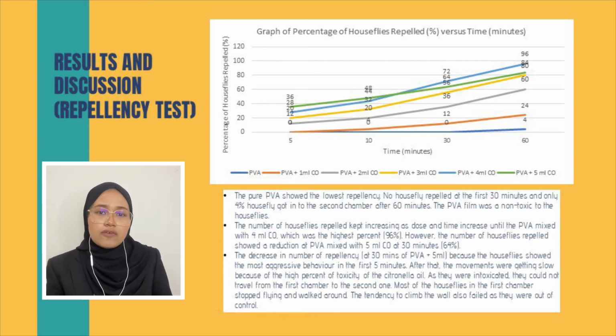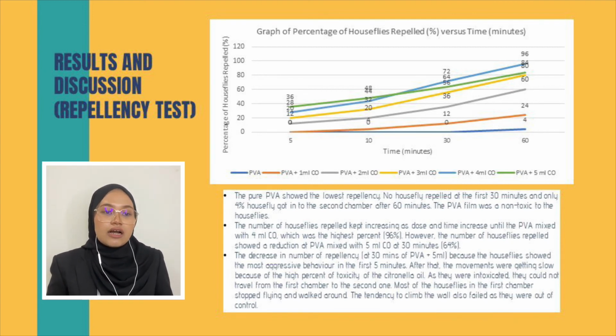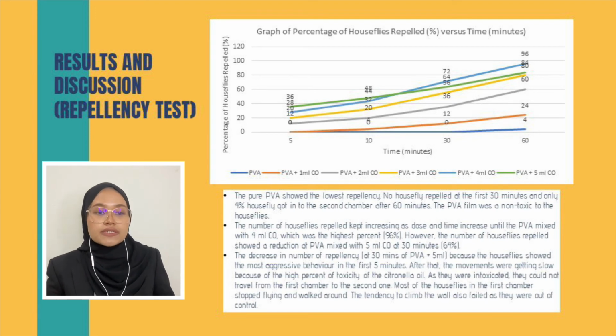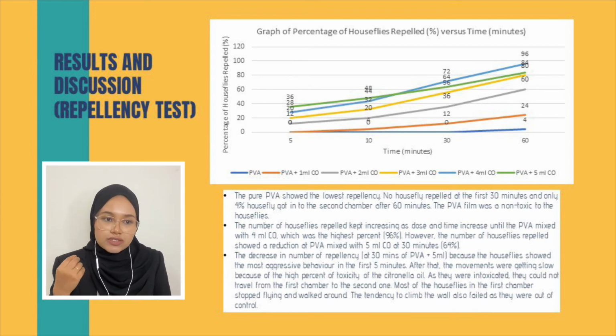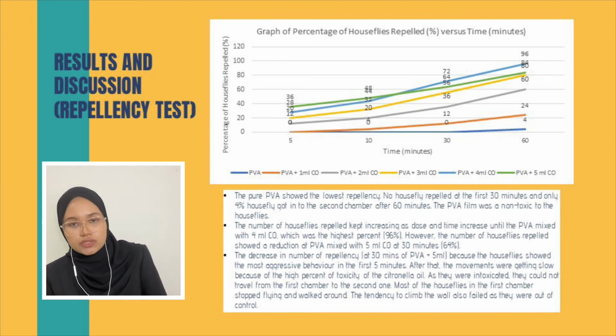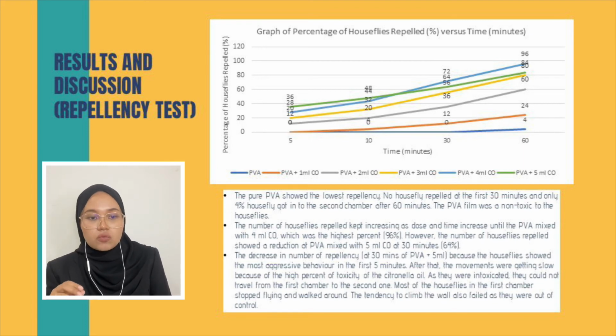However, the number of houseflies repelled showed a reduction at PVA mixed with 5 ml CO at 30 minutes, which is 64%. The decrease in the number repelled is because the houseflies showed the most aggressive behavior in the first 5 minutes. After that, the movement was getting slow because the high toxicity of citronella oil had intoxicated their bodies. They could not travel from the first chamber to the second chamber. The tendency to climb the wall also failed as they were out of control.